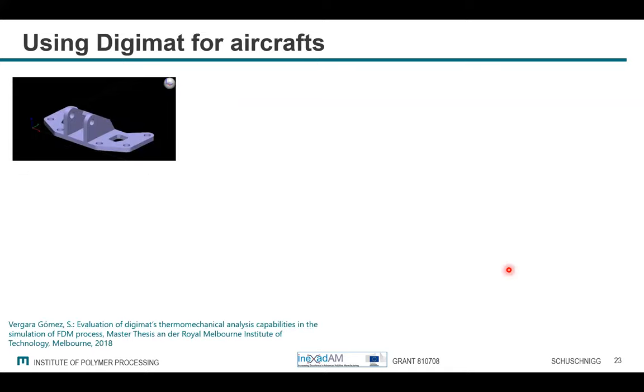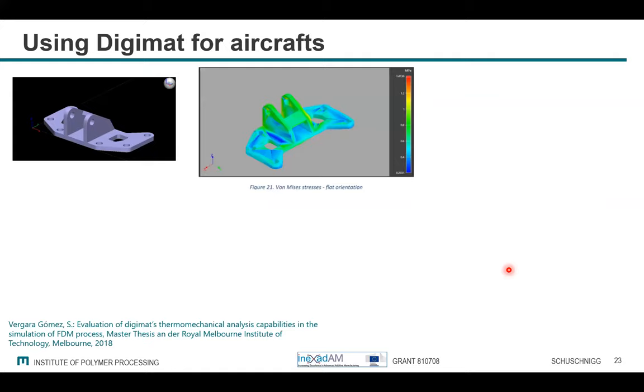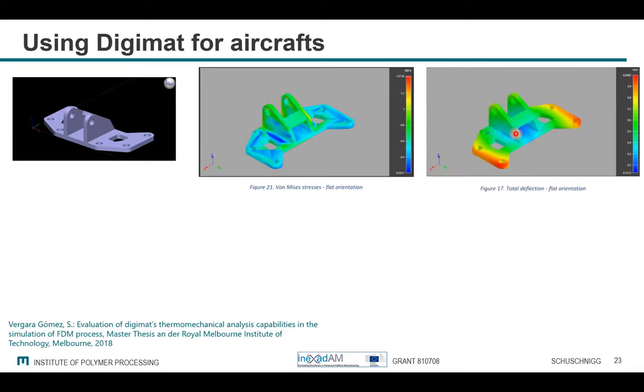On the other hand, Digimat, for example, out of an aircraft hinge, Digimat is used for minimizing the warpage, which always happens. In this case, they have the Ultem polyetherimide used for it, and they put inside the simulation also the printing and the temperature development out of it. Here's the total deflection. This is clearly heavily depending on the orientation of the part in the build itself, because here it's just flat, but you can also put it in other directions.